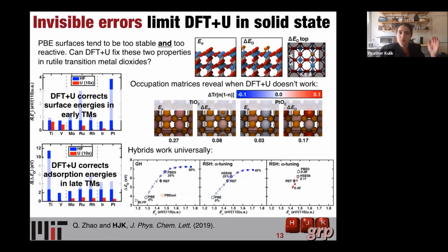So where does the projection get evaluated from? Which pseudo potential did you use? I think you should worry more about, are you extracting Hubbard U values recommended in the literature from someone who used a different pseudo potential than you did, and that can be, I think, even a bigger source of disagreement. That being said, if the hybridization environment is the same, if the thing you want to fix is the same,